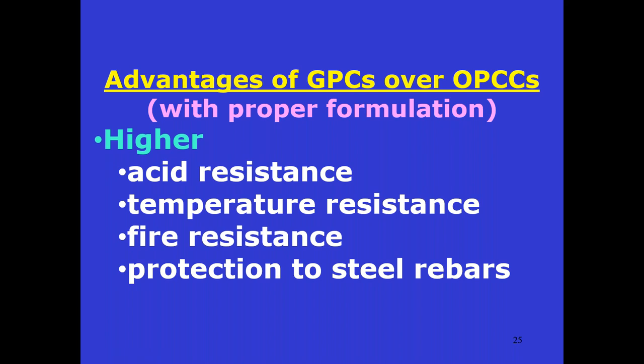Okay. I want to put one point here, which David Woods has written nicely. Why the protection of steel in concrete is more in geopolymer is, even at the end, when carbonation occurs, the carbonation material is only sodium carbonate here. Whereas in ordinary concrete, the carbonate is calcium carbonate. And calcium carbonate pH is around 10 to 11, whereas sodium carbonate pH is more than 11, nearly 12. That means we are having an alkaline environment even after sodium carbonate is formed. That means we are having protection to the steel even after carbonation. So carbonation is not a big issue in geopolymer. Let us remember that point.